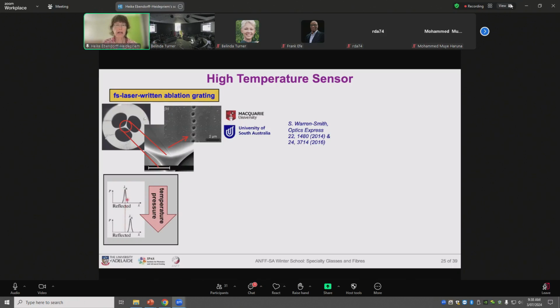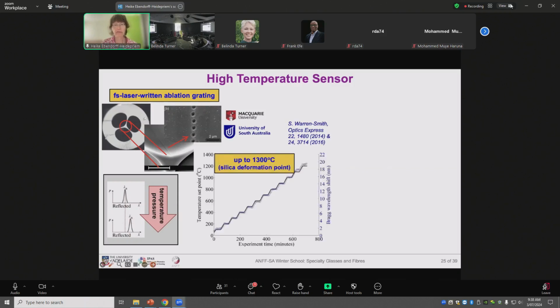So first, the grating means that when broadband light is launched into the fiber, one looks at the reflected light, and only one wavelength is back reflected. It's really given by the periodicity of this fiber Bragg grating and also the refractive index of the glass. Now, if the temperature or pressure is increased, the refractive index of the glass changes slightly, and this changes the wavelength of the back reflected beam.